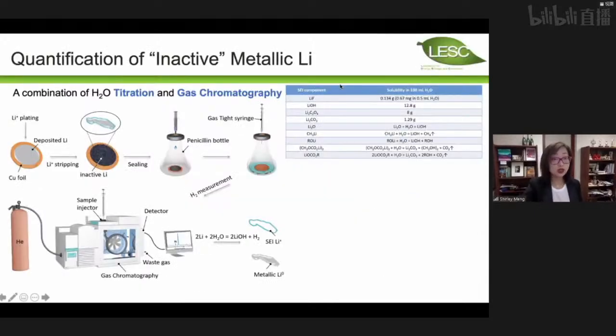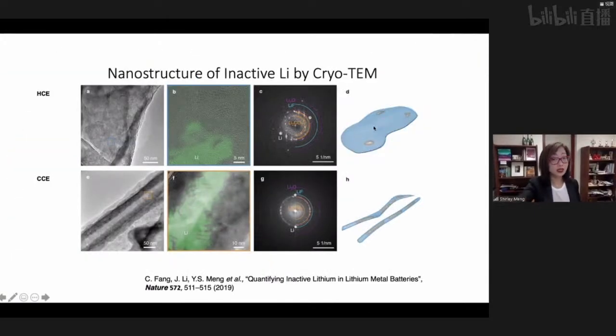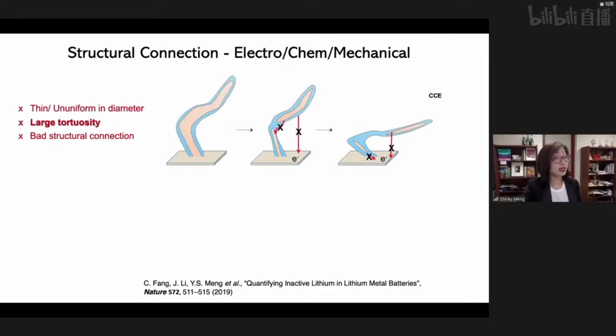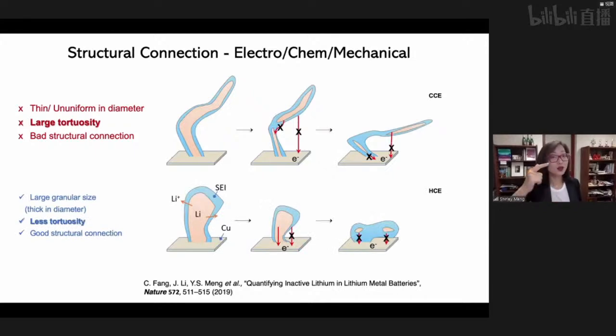So under those conditions, you can image lithium metal, and you can see that if you have large granular particles, very little lithium gets stuck in the SEI. But if you have those kind of tortuous, very elongated, high aspect ratio lithium metal, it's very highly likely you will run into the situation where the lithium metal loses its structural connection with the current collector. So for electrochemistry, right, you need both the ion pathway and the electron pathway. If the blue part, the SEI, is too insulating, you cannot actually access the very good electrochemical system.